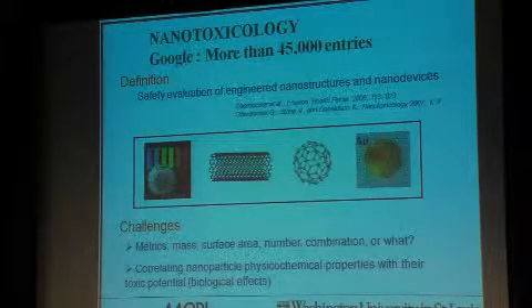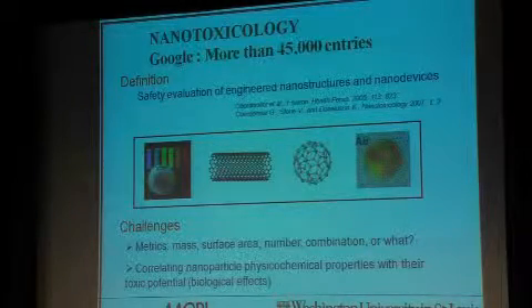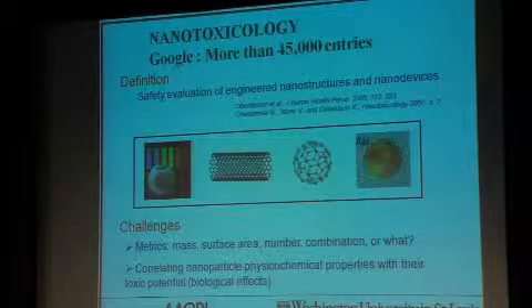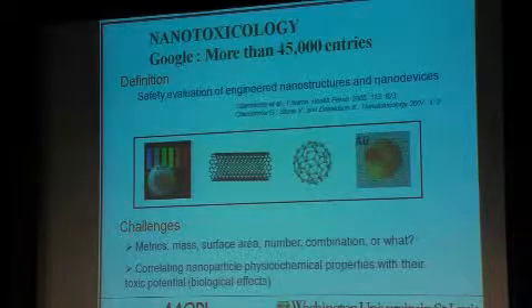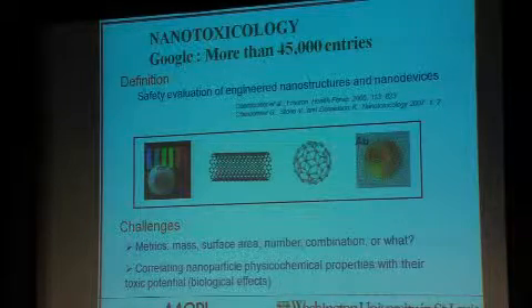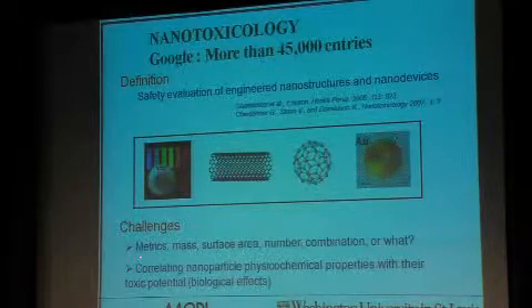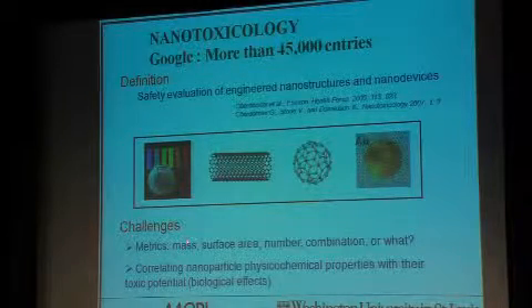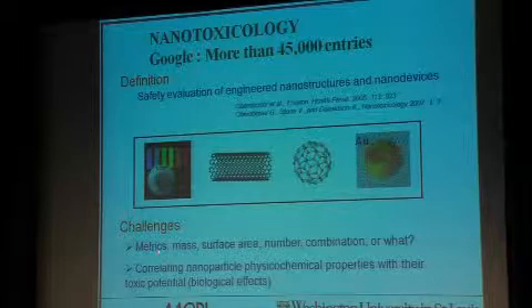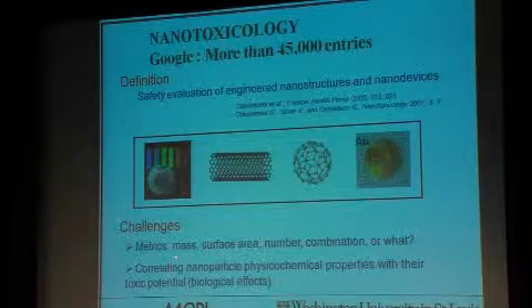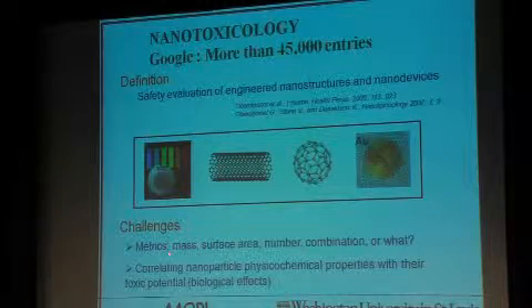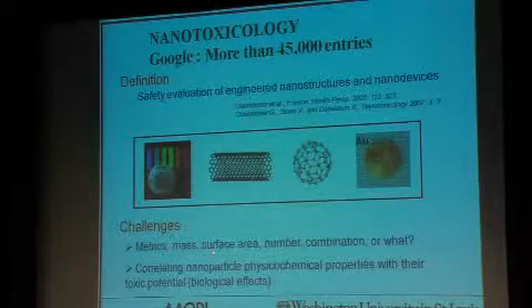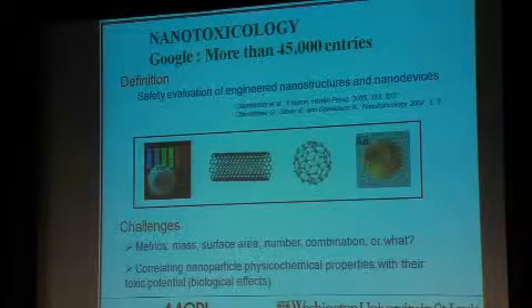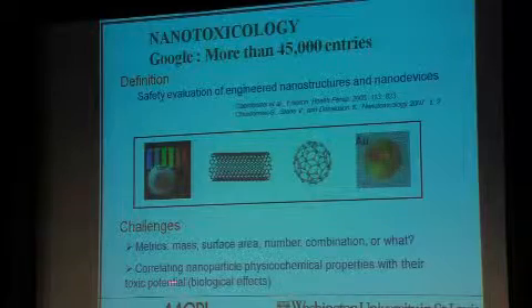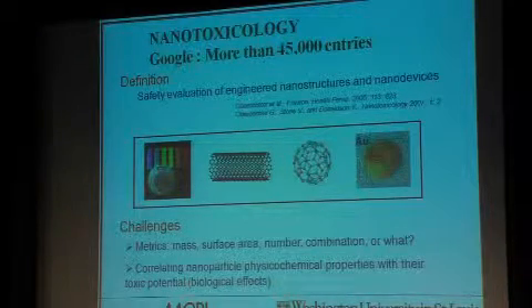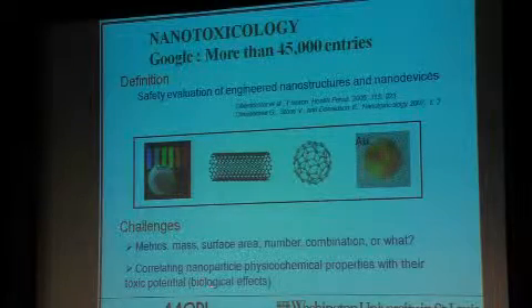One is this issue of metrics, and even the nomenclature. I heard sitting in several talks what nomenclature should be used. There was a talk from our colleague from the medical sciences, and he kept using agglomerate and aggregate interchangeably, and really we need to come up with some terminology which allows us to really understand each other well. And then, of course, eventually the metrics, which was brought out very well, I think, by Patricia. Do I use mass? Most toxicologists use a certain mass concentration, but should it truly be surface area or number or a combination or something like that? All of this would be possible if I can really correlate nanoparticle properties to the biological effects, right?